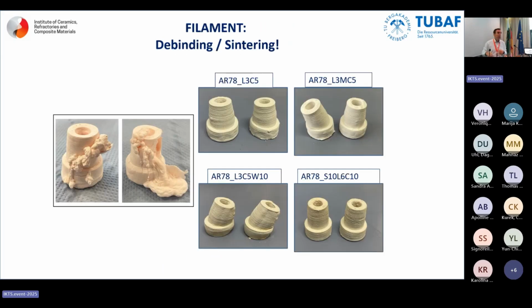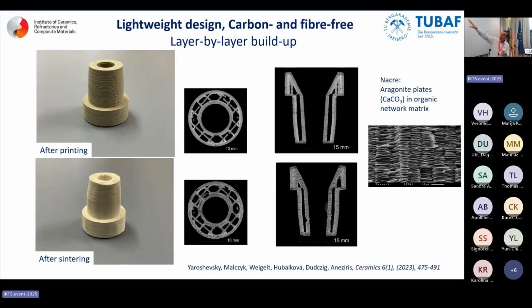Of course, up to coming to this moment, you can make errors in the beginning, as we see on the left. Perhaps the price is much higher than the original. But at the end of the day, if you control the debinding and especially the sintering, you can create such kind of nozzles after printing, after sintering. You have an inside with special properties, a light structure between the outer. It could be that the outer is like a belt and puts the inside under compression, so you improve the thermal shock performance in one way.